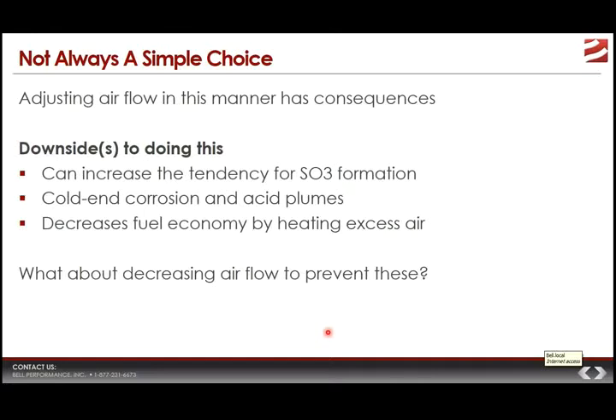The first downside, which is not illustrated on the slide, is the slide we looked at a few minutes ago, where we talked about vanadate formation. What we saw was that if you increase the oxygen amount above 3.5 to 4%, you dramatically increase the amount of vanadate deposits formed in your boiler. So that's consequence number one. Downside number two is that adding more oxygen means you get more SO3 formed, because you have more oxygen available for SO2 to further react with. Downside number three, you get a higher incidence of cold end corrosion and acid plumes. And an unintended consequence is that you can actually decrease your fuel economy.